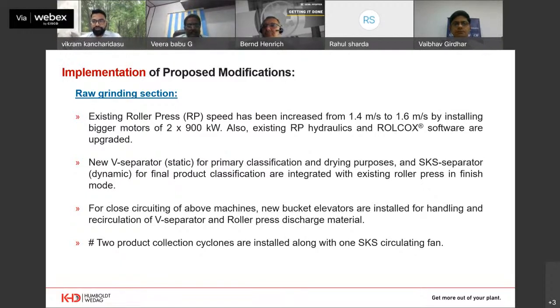And also the motors were not suitable. Then we have replaced the motors with bigger capacity, 900 kilowatt. The RP hydraulics and the ROLCOX® software, the latest generation, have been upgraded in the existing system. As I already showed in the flow sheet, the existing system has this pneumatic hammer mill for the drying. Now we have a V separator for the drying purpose as well as for the primary classification purpose. We have installed a V separator, and for the higher capacity, one new dynamic separator is also installed. And these are incorporated in the finish mill circuit with the existing roller press.